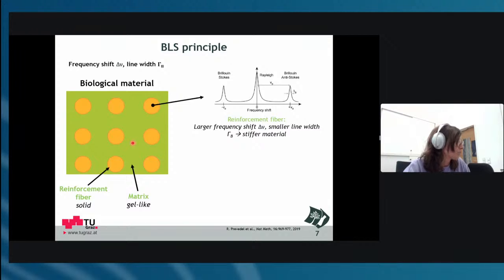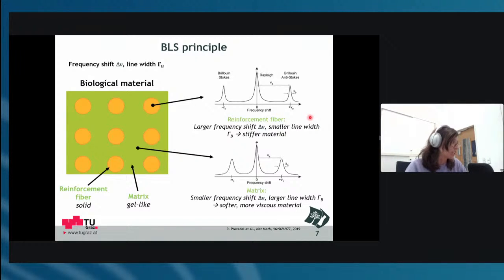But if you just measure this reinforcement fiber, which is a solid material, we will usually get a larger frequency shift. So the peak will be further away from the zero line, this large Rayleigh line, and the peak will also be very narrow. So the line width is small, and this is an indication of a stiffer material. So usually when the peaks are more narrow and further away from zero, the material is stiffer. In comparison, if you just measure the matrix, you get much smaller frequency shifts. They move closer to zero, and the peaks are much broader. They have a larger line width.